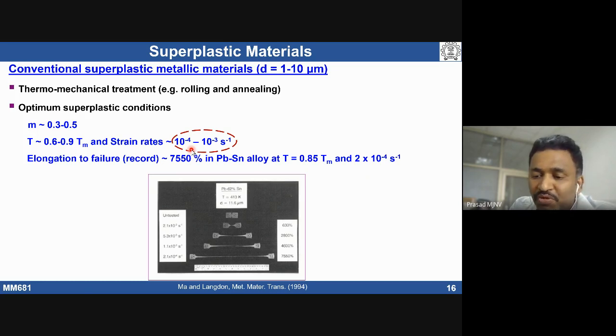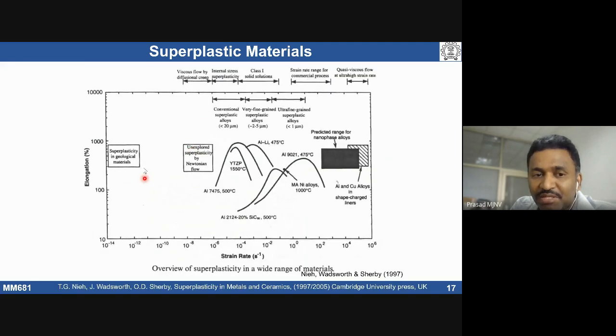People have shown a diagram, schematically, of percent elongation as a function of strain rate. Our requirement, from a production point of view, is to go towards higher strain rates. If a material exhibits superplasticity at high strain rates, that is the best thing from a commercial point of view. So what people have said is that if we refine the grain size, we can push the strain rate domain towards the right, towards the higher side. Based on different materials and their grain sizes, it was shown that if we refine the grain size, we can get high strain rate superplasticity.